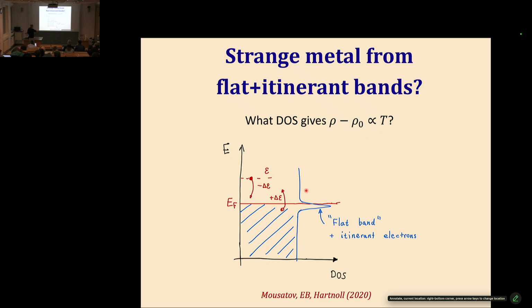And there is a region of the band structure which is very flat, close to the band edge. The trouble is that it turns out that, quite fundamentally, this behavior actually cannot extend down to the lowest temperatures. If you just assume this sort of weakly interacting model and calculate the entropy of the system, it has a finite offset. If this would extend all the way down to the lowest temperatures, it would violate the third law of thermodynamics.